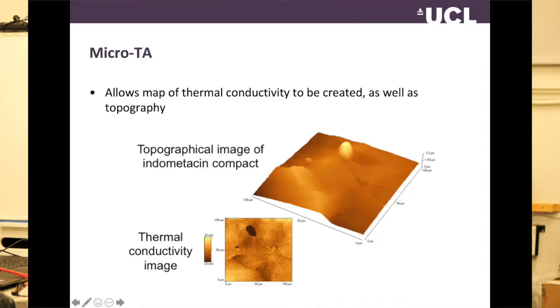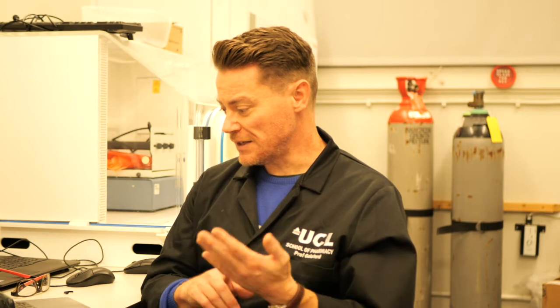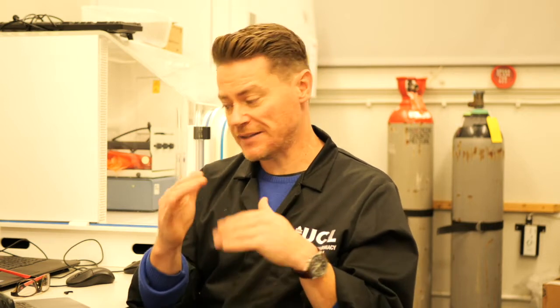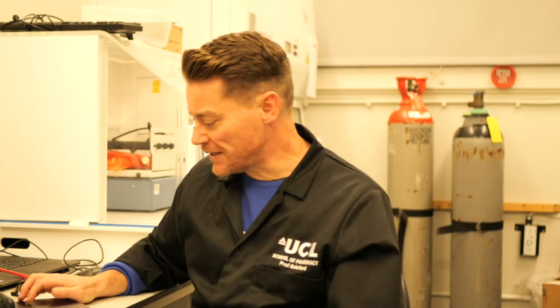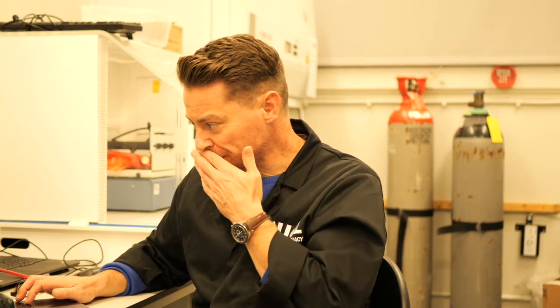If you then make a thermal conductivity map of that sample, which is the smaller image towards the bottom, then you can see that the majority of that tablet is colour-coded yellow-orange, and there's one region which has got a sort of darker brown blob, for want of a better word. And so that's kind of implying that there's something there which is different. Most of the tablet is homogeneous, but there's something stuck in the surface of the tablet which is behaving in a different way. Can we try and interrogate the surface of these materials and try and work out what that is?